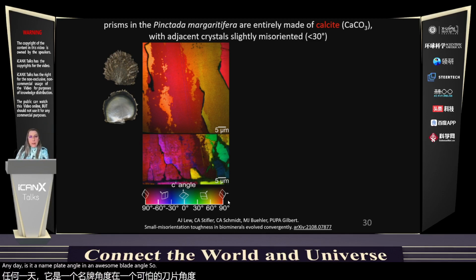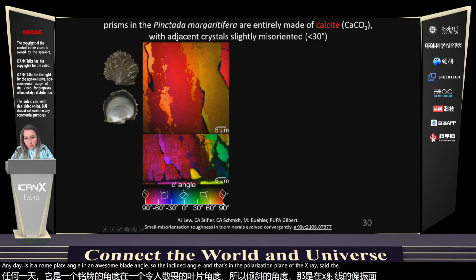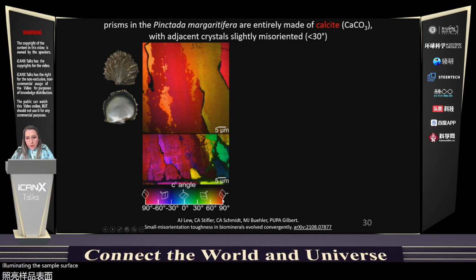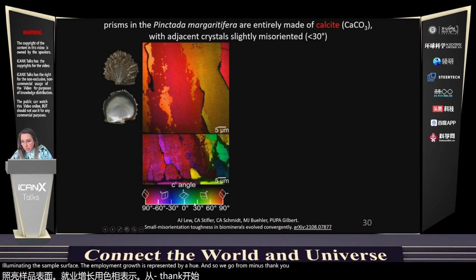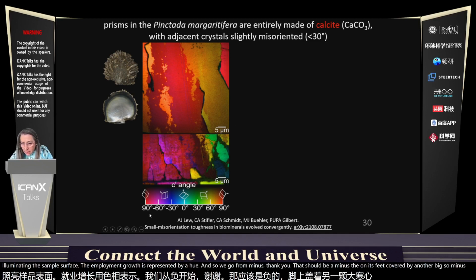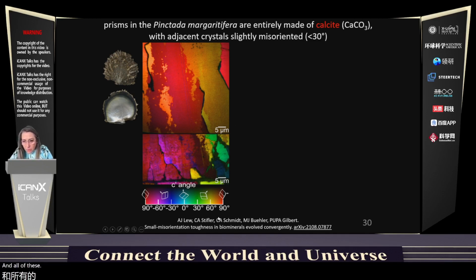So the in-plane angle, and that's in the polarization plane of the X-rays that are illuminating the sample surface, the in-plane angle is represented by hue. And so we go from -90, there should be a minus there, it's being covered by another image. So -90 to +90, and all of these hues in between, so red, magenta, blue, and so on.